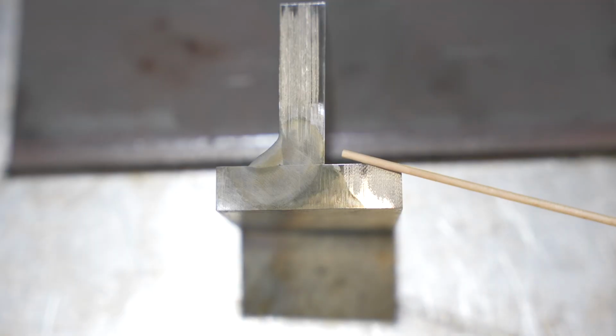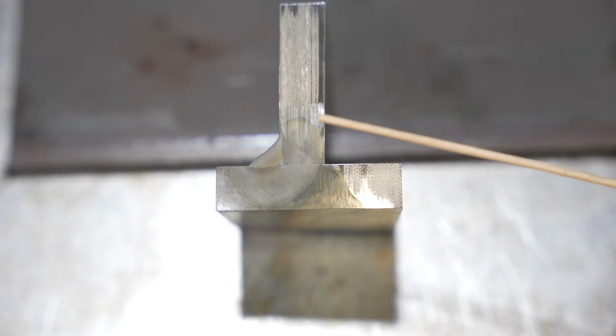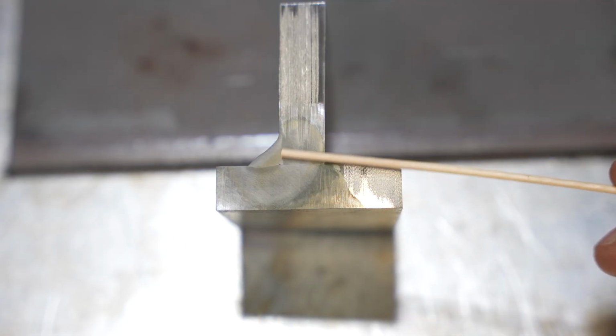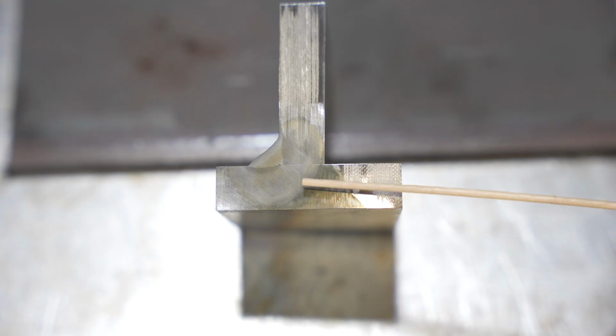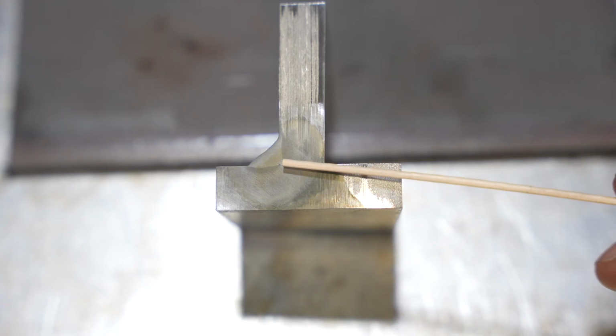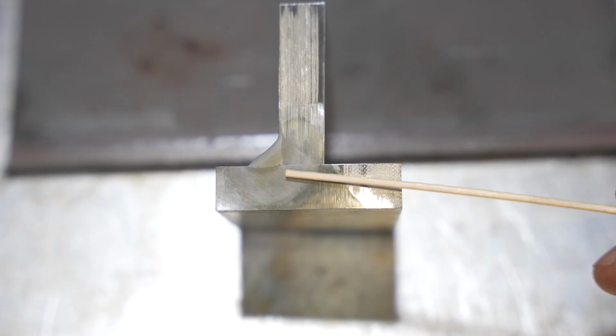So I've etched the weld here on this 1/2 inch thick plate once again, and you can see I did get some penetration into the vertical plate and into the horizontal plate on this thick material, and it did just barely come down and kiss that corner of the weld. So this is in the acceptable region, but I wouldn't mind a little bit more penetration. I think with a little bit hotter settings, I could probably get there.